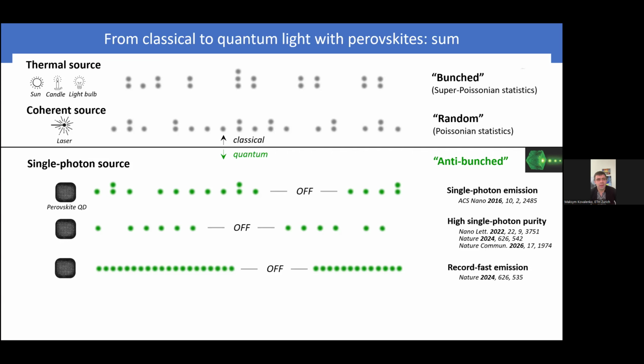Dmytro, first of all, great to see you again. And why not? Lead, there is not so much choice because lead is supposedly good for a number of reasons. It has good spin-orbit coupling, and that somehow improves the band dispersion in conduction and valence band. So it's good for semiconductor, actually, good strong spin-orbit coupling. And then another one you would expect to do similar would be bismuth, but bismuth is three-valent. And so when you try to make halides of those, you don't get the same structure. You don't get corner shared structure. You get face or edge shared, non-perovskite lattice. So different crystal structure gives you different band structure. And so we are just quite restricted to lead.